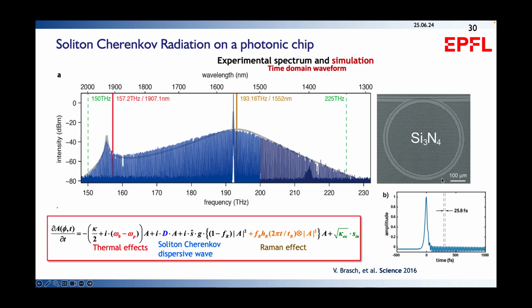The challenge still is that microcombs really shine at very large rep rates. Making a repetition rate of a terahertz is extremely easy because the thresholds are low, but bringing down the repetition rate to a few tens of gigahertz causes the soliton process to be rather inefficient, and also you need to align F-to-2F. If your f_ceo suddenly gets 50 gigahertz or 49 gigahertz for a 100 gigahertz device, it becomes challenging to detect. That's why microcombs, in terms of clockworks, require a more complicated architecture. You need one comb that's very broadband to give you an octave, and a second comb to measure the repetition rate. This has been shown in the work from Scott Papp and Kartik Srinivasan, that you can make a frequency synthesizer, so generate an arbitrary frequency, or use it in a clockwork application.